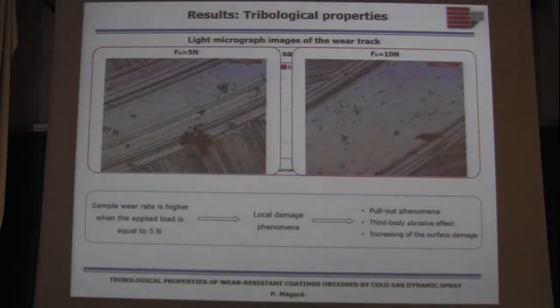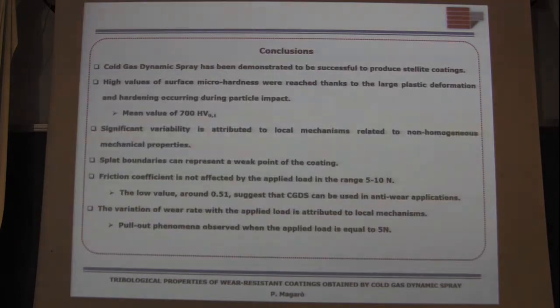In fact, on the wear track observed for the test carried out under a load equal to 5 Newton, the pull-out phenomena can be observed. But in the wear track of the samples tested under 10 Newton load, the surface seems to be less affected by this kind of phenomena.